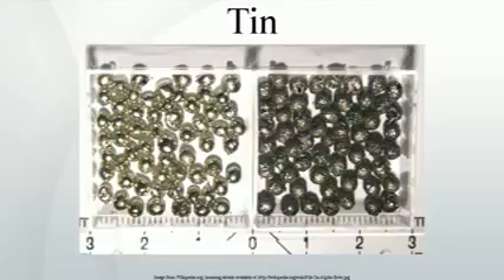Commercial grades of tin, 99.8%, resist transformation because of the inhibiting effect of the small amounts of bismuth, antimony, lead and silver present as impurities. Alloying elements such as copper, antimony, bismuth, cadmium and silver increase its hardness. Tin tends rather easily to form hard, brittle intermetallic phases, which are often undesirable.